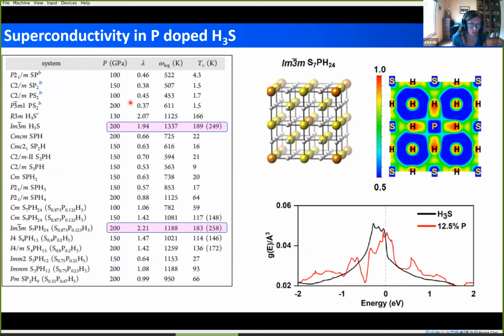What I note here is previous work done just on sulfur phosphorus. If we add just one hydrogen to it, you can really raise the TC by an order of magnitude.